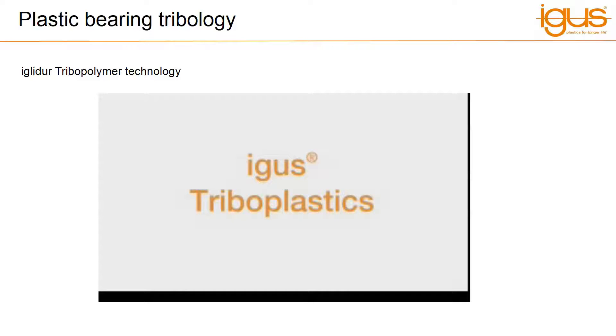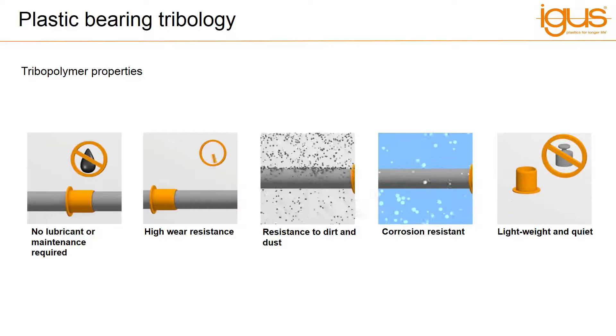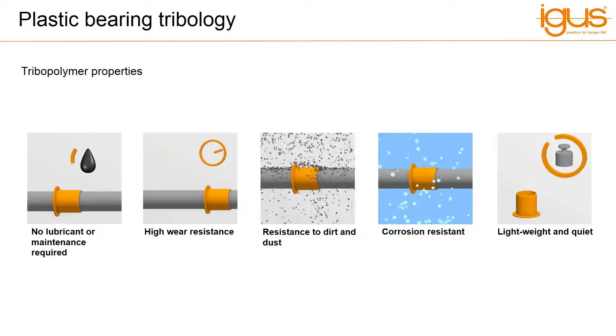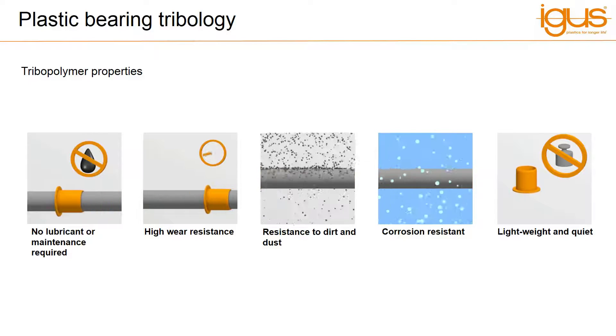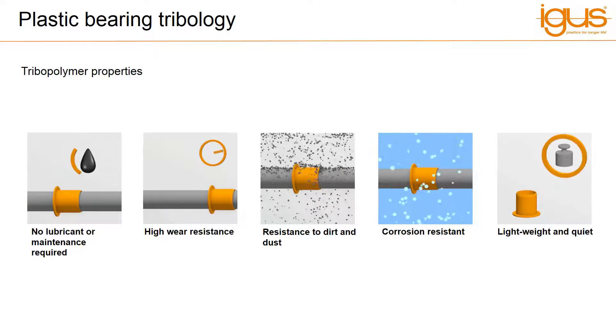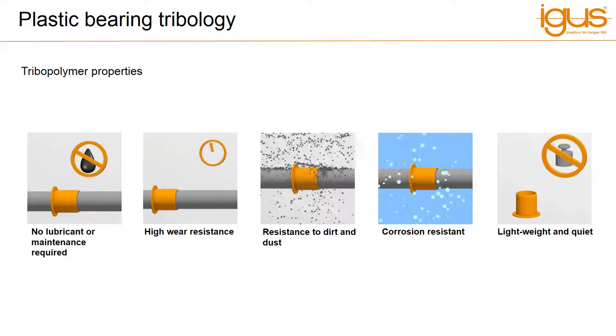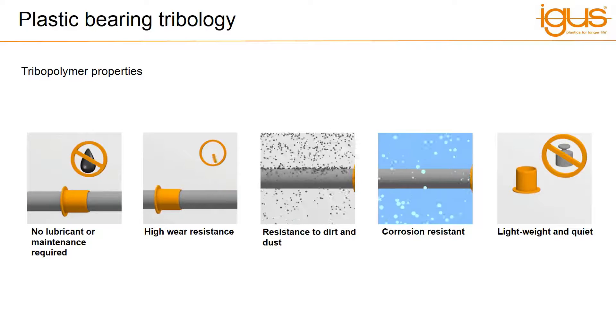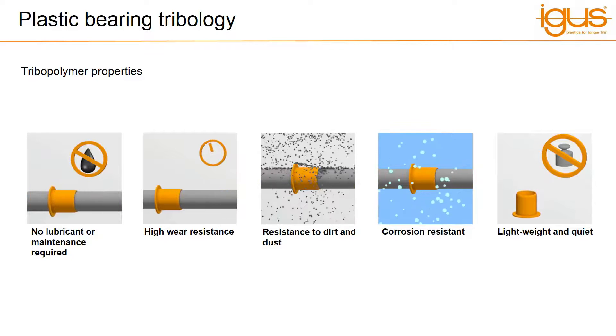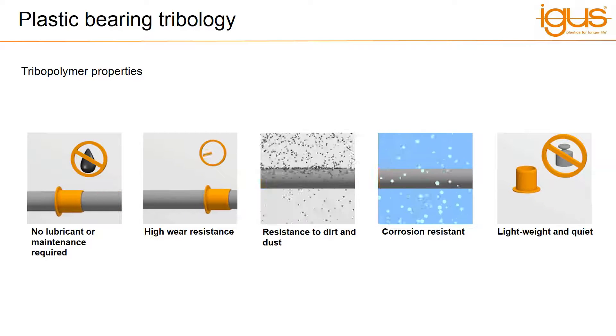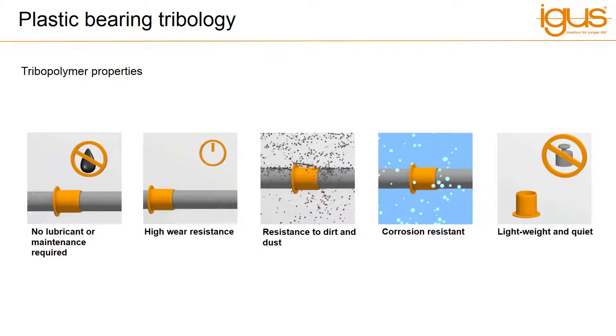Tribopolymers are manufactured to support the properties throughout the material thickness, not in layers as in some more traditional materials. This means the tribopolymer blend is homogenous, ensuring materials are linear in both their wear and friction characteristics, so predictability is maintained, eliminating the risk of catastrophic failure. The key points for homogenous materials such as the IGLIDUR range from igus are: dry running — absolutely no external lubrication required due to internal solid lubricants; maintenance free as a result; high wear resistance and strength due to the reinforcing fibres within the materials; and resistance to dirt and dust, primarily because lubricants are avoided, enabling dirt particles to fall away instead of adhering to a lubricant coating on the shaft or bearing.